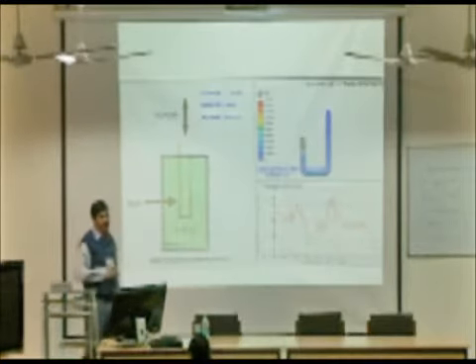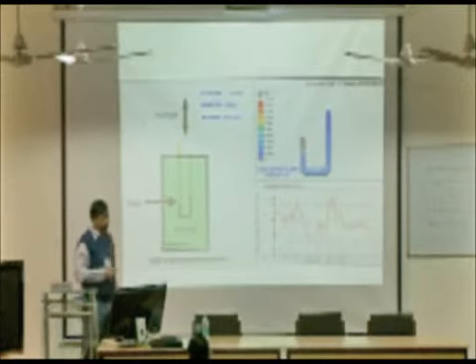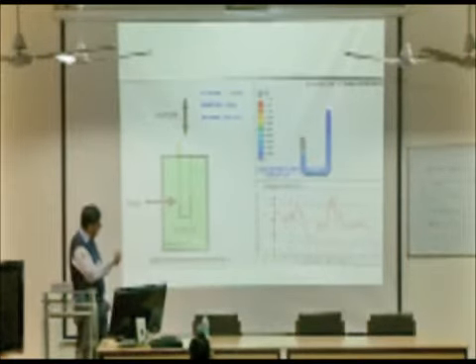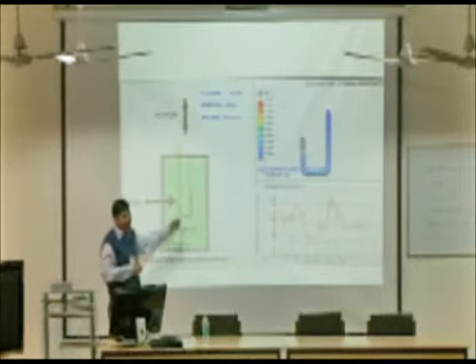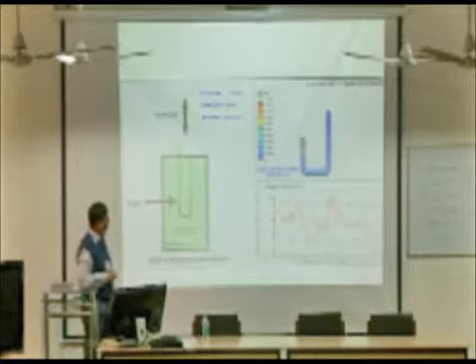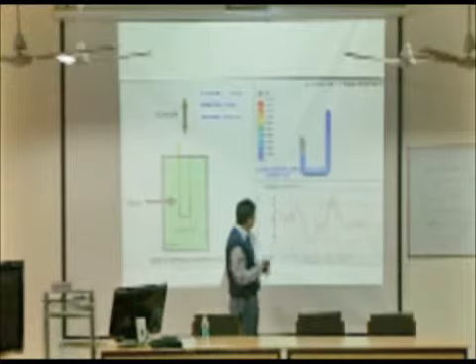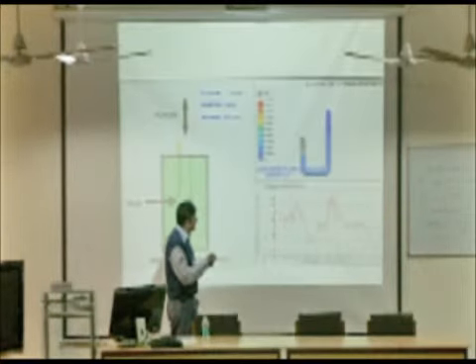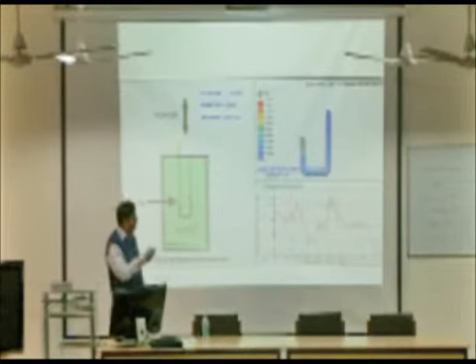One more option that we have tried is this kind of design, a U-shaped die, but it has some problems for commercialization. Again, the billet gets stuck inside. But in this we are able to obtain a very high amount of equivalent strain. Here we have taken 2 kinds: at one place we have given a chamfer, in the other a curve, and we have seen that equivalent strain is affected by this small parameter also.